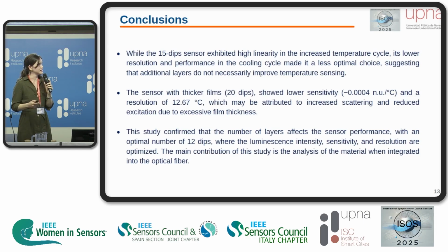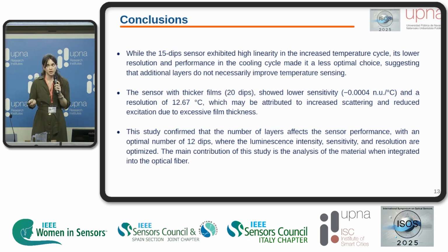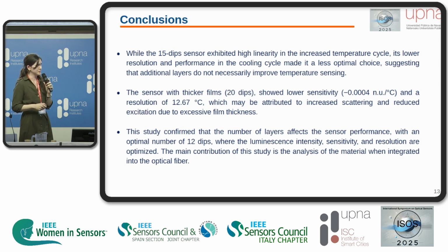With these results, we can say that while the sensor with 15 dips exhibited a high linearity in the increasing cycle, its lower resolution and performance for the cooling cycle made it a less optimal choice, suggesting that additional layers do not necessarily improve temperature sensing. The sensor with thicker films, in this case with 20 dips, showed lower sensitivity and resolution, which might be attributed to the increased scattering and reduced excitation due to excessive film thickness.